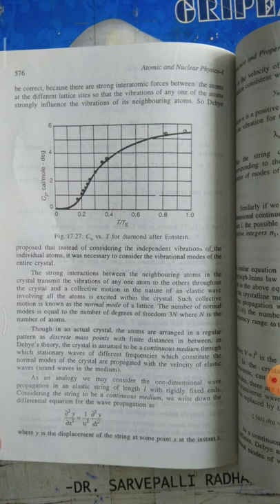So Debye proposed that instead of considering the independent vibrations of the individual atoms, it was necessary to consider the vibrational modes of the entire crystal. The strong interaction between the neighboring atoms in the crystal transmits the vibrations of any one atom to the others throughout the crystal, and a collective motion in the nature of an elastic wave involving all the atoms is excited within the crystal. Such collective motion is known as the normal mode of a lattice. The number of normal modes is equal to the number of degrees of freedom, 3N, where N is the number of atoms.